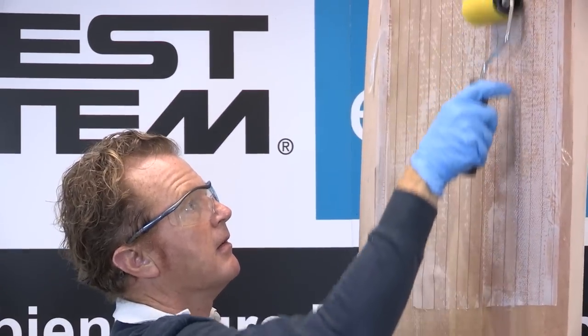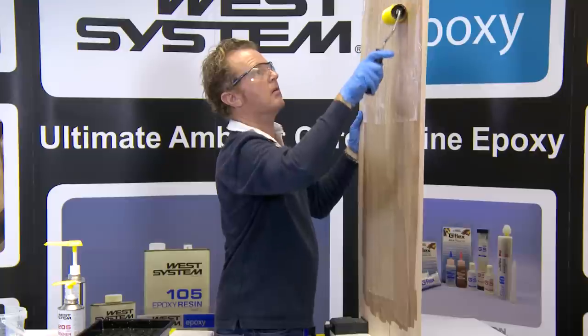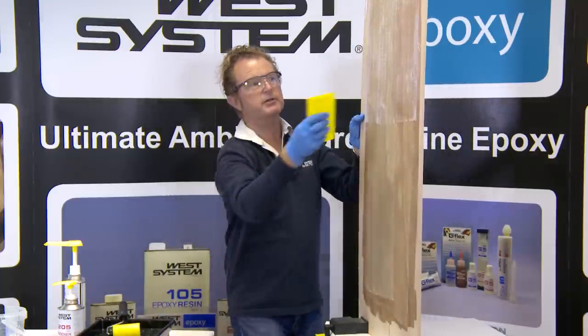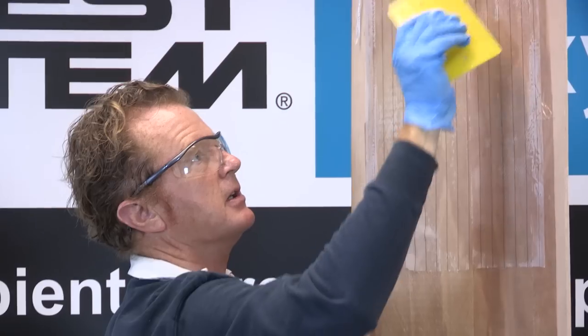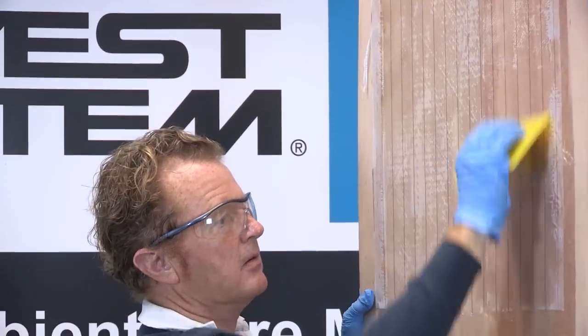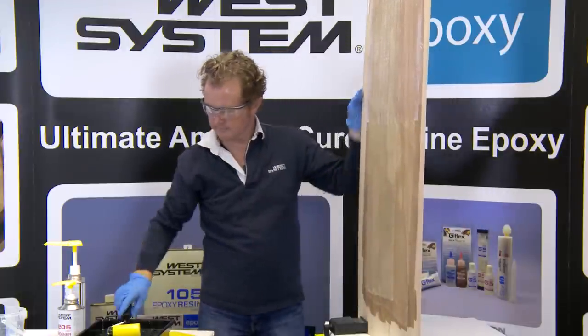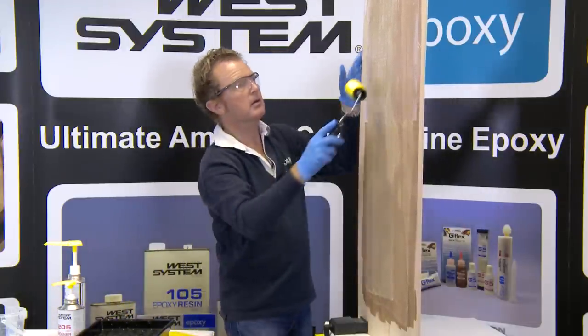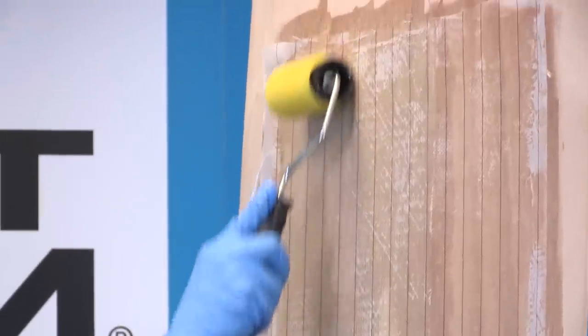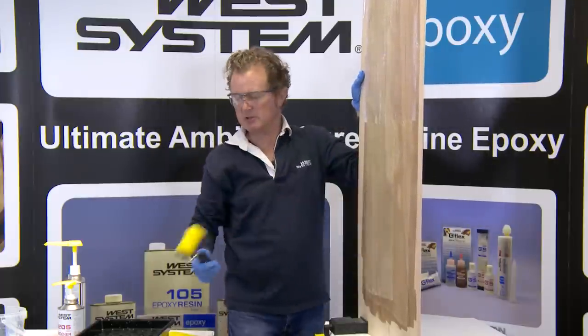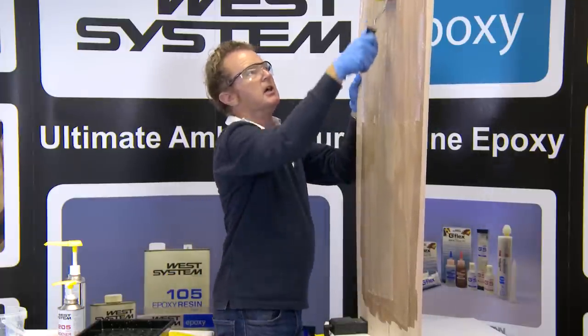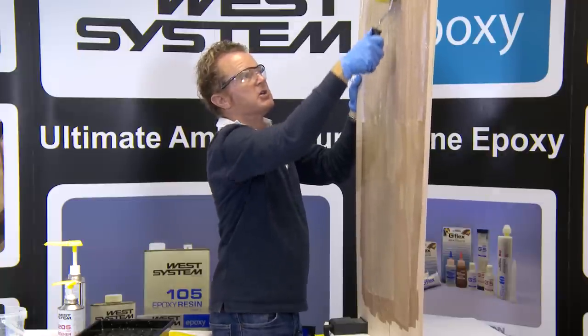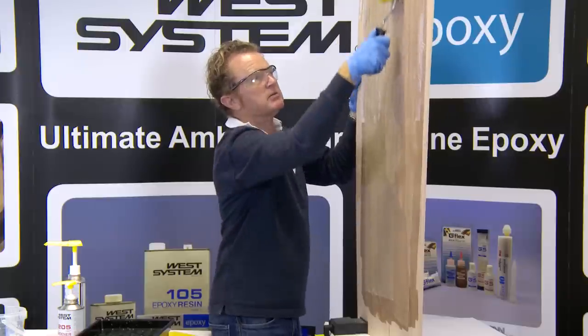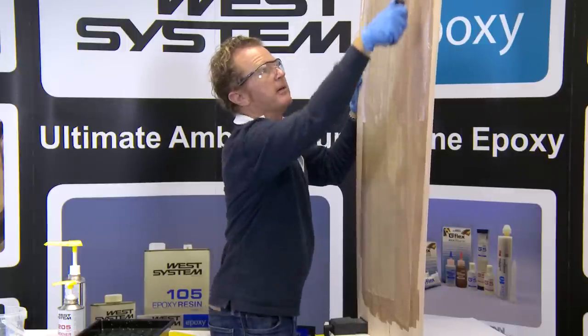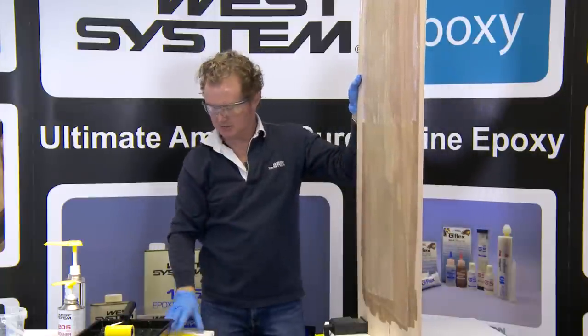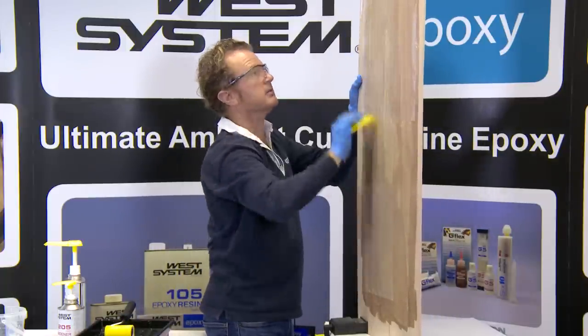It's important that I just make sure that this is nicely wet out, and I can finish this off with my plastic squeegee. And you can see here, there's absolutely no problem in applying just a little bit more epoxy over the peel ply, just to ensure that it's all wet out. Because if it's not in contact with the wet surface underneath, it won't function and do its job, because it won't leave an impression of the texture of the fabric in the wet epoxy.